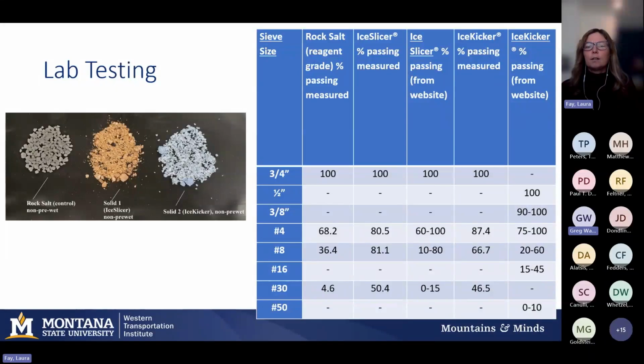What we found was that the reported gradation on the website does not match necessarily what we actually had in the sample. There was a significantly higher amount of fines in the ice slicer. And again, for the ice kicker, they reported on their website slightly different sieve sizes, but categorically they matched, but again, still a much higher amount of fines than what was in the lab grade product.